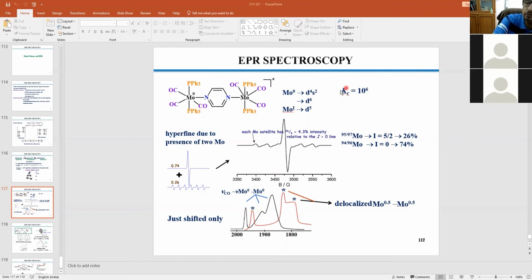Okay, and also if you look at the Kc, what you calculate from your electrochemistry, that is also giving 10 to the power 6. Now, electrochemistry is much slower. So if we compare the experimental rate, this is the slowest one. That tells you delocalized scenario. That's why I gave you this example, Kc. So that tells you delocalized. EPR, 10 to the power minus 8, this is in terms of minutes actually. Yeah. So in terms of minus 8, it is telling you delocalized, and then IR, if you go to 10 to the power minus 12, again it is delocalized.